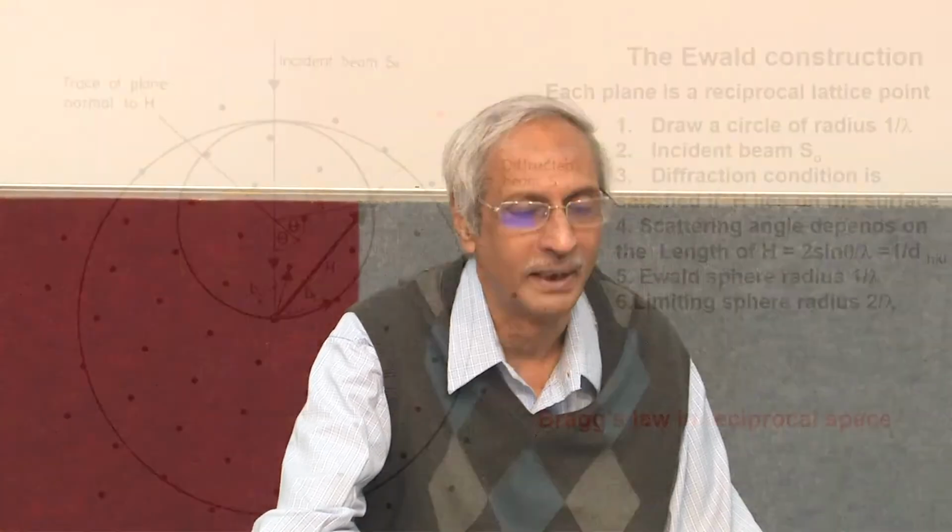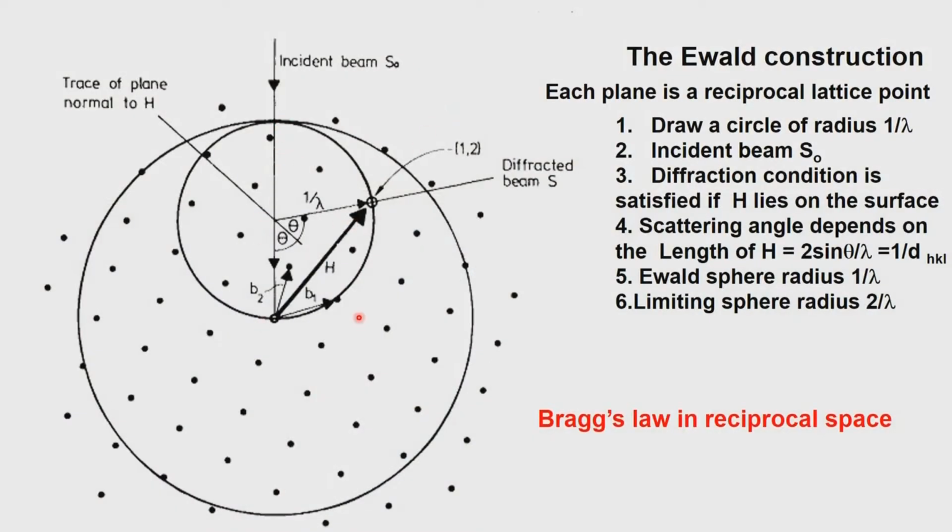It may so happen that as you rotate the crystal, there may be positions with more than 3 or 4 reflections satisfying the Bragg condition. Then at that particular angle of rotation of the crystal, you will get more than one reflection. So, it is not necessary that one at a time should come, you can get any number of reflections at a given angle theta in different directions. See, the directions are different; let us say this point and this point were to intersect, we will get one diffraction in this direction, another diffraction in that direction, and so on. So, it goes in that particular fashion.